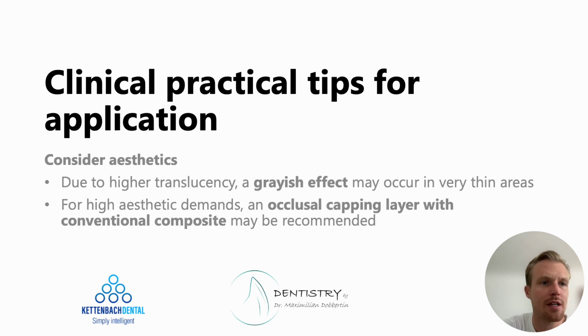And then we have to consider the aesthetics, even in bulk fill composites. Due to higher translucency, those bulk fill composites sometimes have a little bit of a grayish effect, which may occur in very thin areas where they meet the enamel, but this is not the case within the newly released Visalys Bulk Fill, as you will see in the following cases. So for high aesthetic demands, sometimes it can be useful to do an occlusal capping layer in terms of more individualization for this specific restoration.